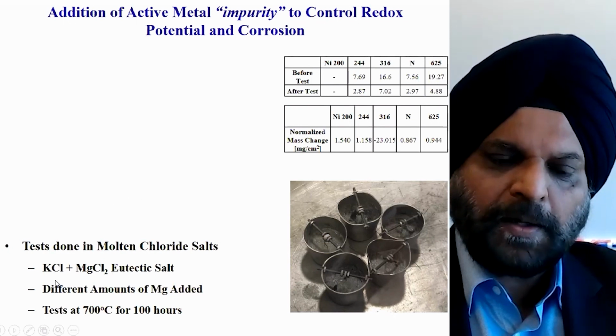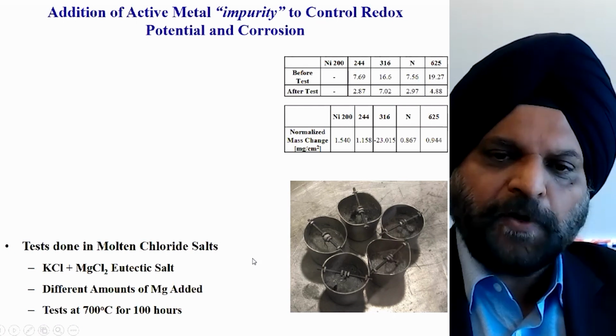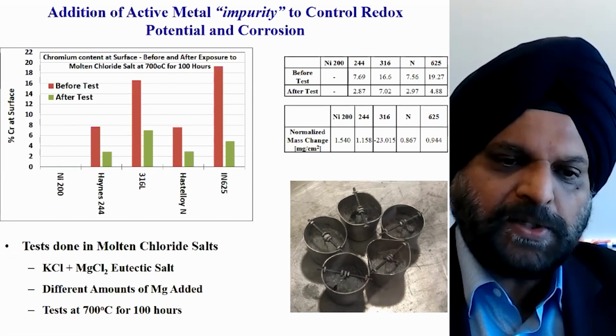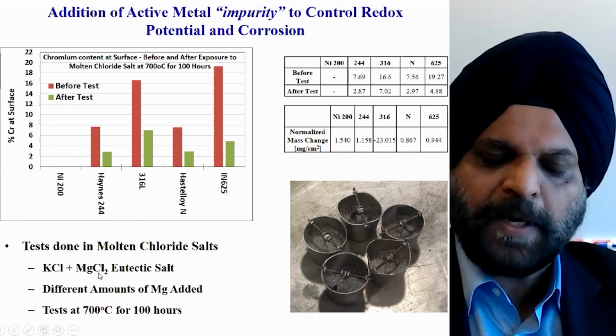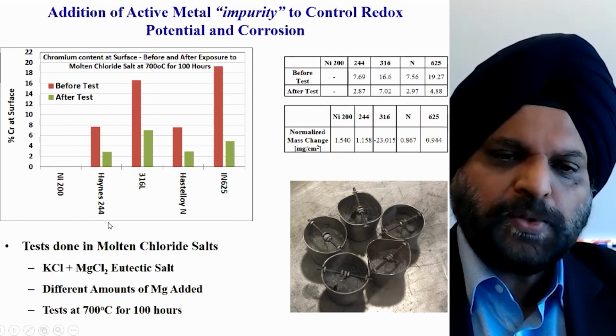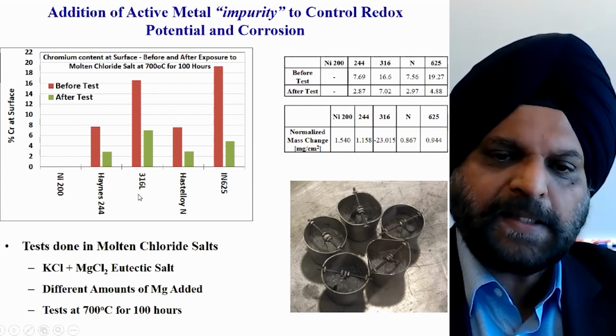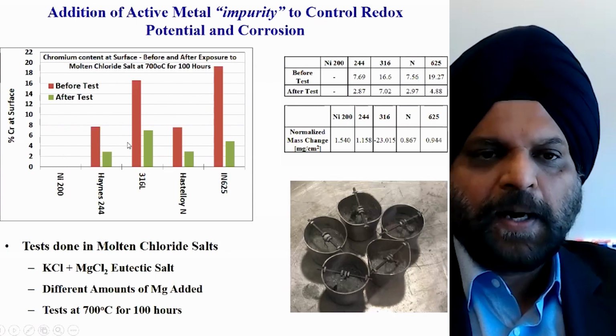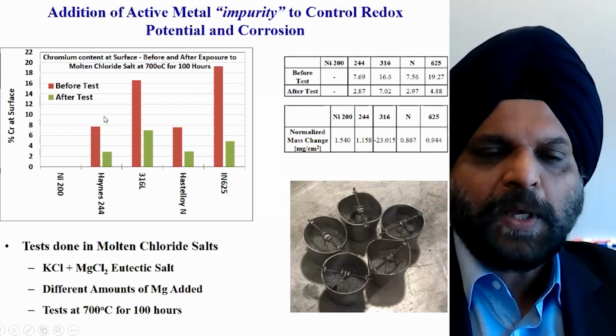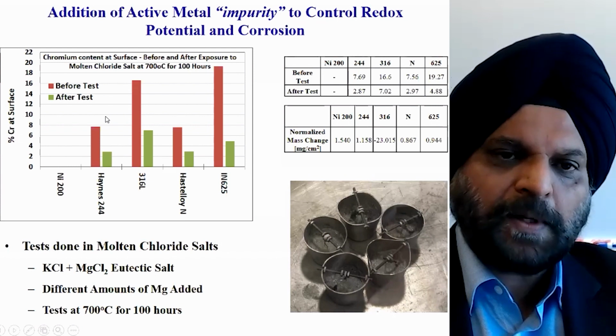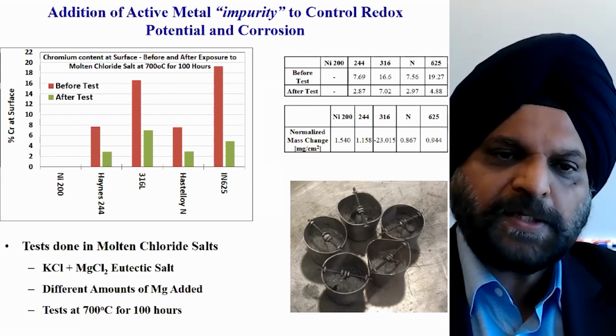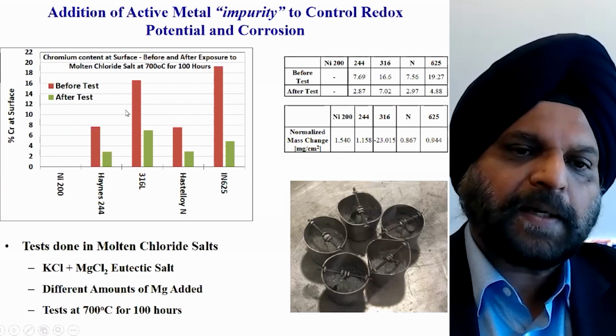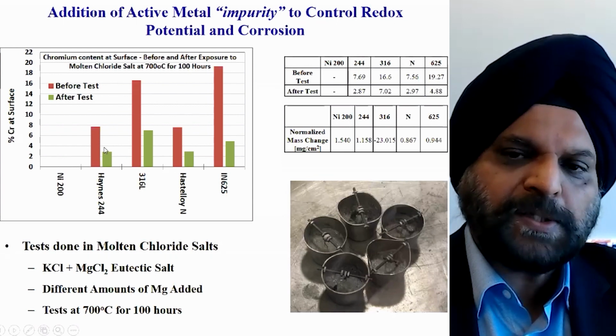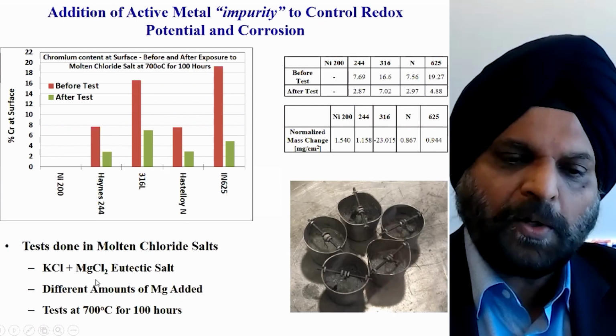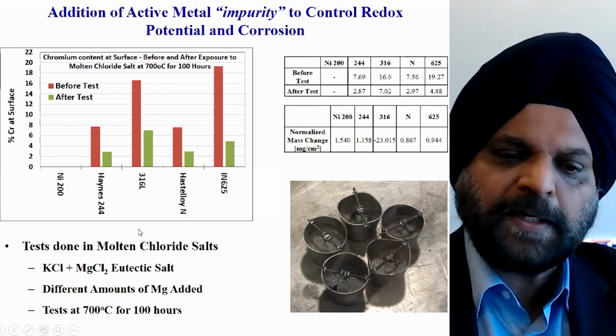The data I'm showing is in chloride salts. If we don't have any magnesium added, just the eutectic mixture of potassium chloride and magnesium chloride, we do some tests with alloys, for example Haynes 244, Hastelloy N, 316, and Inconel 625. The red bars are surface chromium content measured by XRF, the X-ray fluorescence technique. The green ones are after the samples were exposed to this chloride eutectic at 700 degrees Celsius for 100 hours.